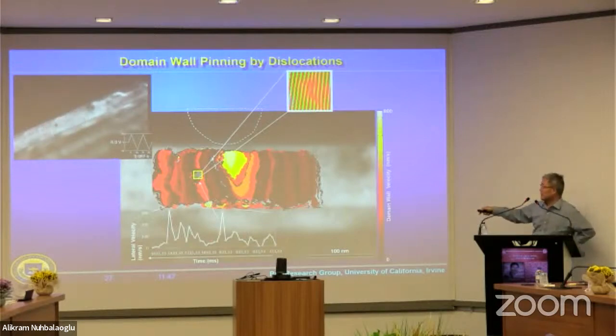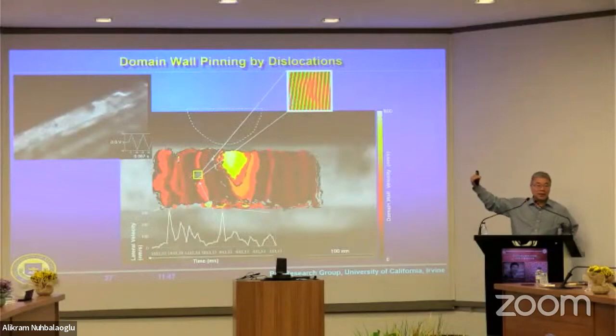The reason for this is that the domain wall moves to here, and this dislocation holds the domain wall, just like a barrier. And then when the electric field increases further, the driving force becomes higher and higher. Eventually the pinning effect of the dislocation will be overcome, the wall passes the barrier and moves further, suddenly very fast, and then slows down. So this is the first demonstration of the pinning and unpinning of a domain wall by defects. All right. So that demonstrates dynamics can be studied in in-situ electron microscopy.